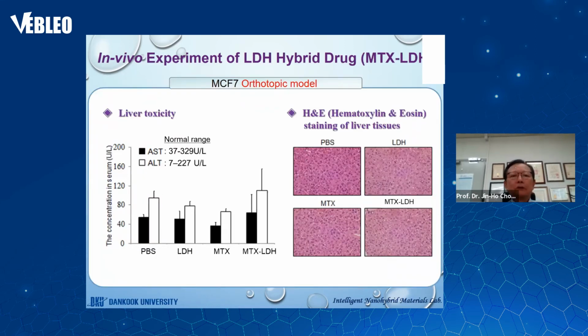Well, according to our biodistribution study, we found that our nanoparticles accumulate in the liver in the first period of time after the injection, but as time goes on, the particles were released out. However, we wanted to check the liver toxicity. For checking the liver toxicity, serum levels of AST, aspartate aminotransferase, and ALT, alanine aminotransferase, were studied carefully.